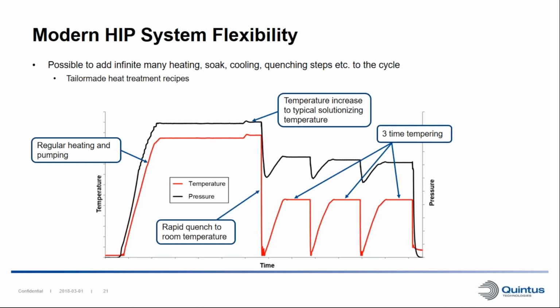I also want to show that a modern HIP system offers a quite high degree of flexibility. It's not only high cooling rates. We can add infinitely many different heat treatment steps into the HIP cycle, for example, a heating step, a soak time, cooling, quenching, etc., to really tailor-make your heat treatment recipe to get the desired properties that you want. Down here we can see a hardening for a tool steel. We have a typical regular heating and pumping step, we have a soak time. At the end of the soak time, we increase the temperature just a little bit before quenching down to room temperature, and then we have a 3-time tempering.